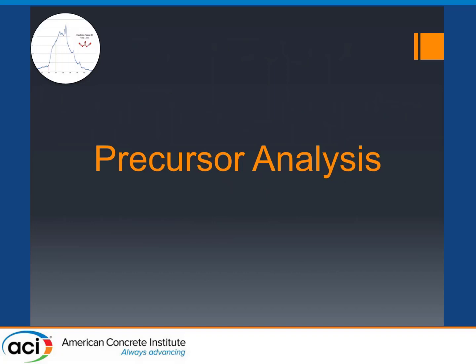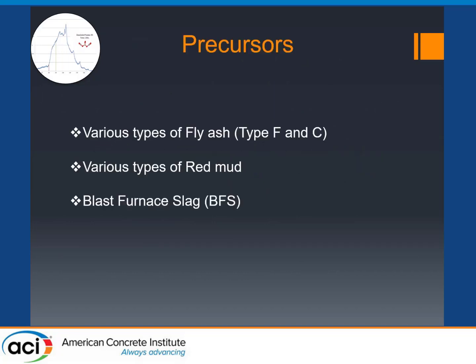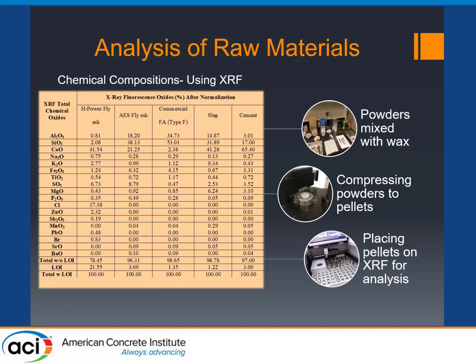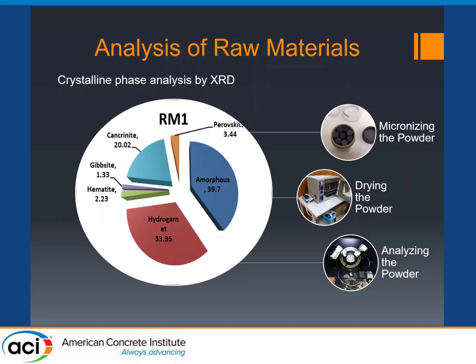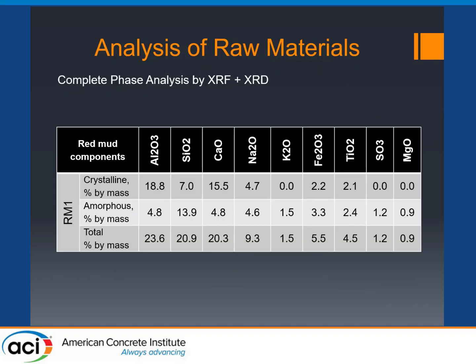All right, so I will quickly go over the precursor analysis using the classic XRD and XRF. This is XRF, this is XRD for different precursors. What we did here is we tried to estimate the percentage of reactive phase and non-reactive phase. We also call that amorphous and crystalline phase. Okay. Combining XRF and XRD, we can have a better estimation of these two phases, as well as the idea of the strength of crystalline phases. This is also very important. I will talk about it in a moment.